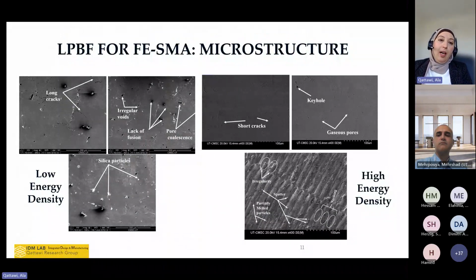We also looked at understanding the microstructure in terms of defects. And then you can see here the extremes of the two windows. If we have low energy density, you can see a lot of defects on the microstructure. We have irregular voids, cracks, and small pores, like particles of unsintered powder, because the dynamics of the melting pool affect the quality of the sintering.